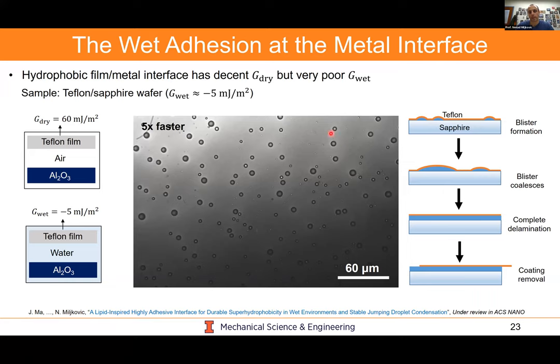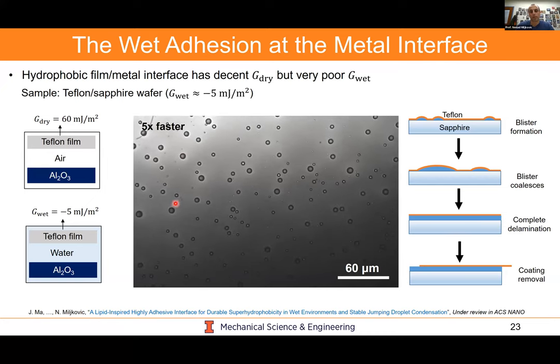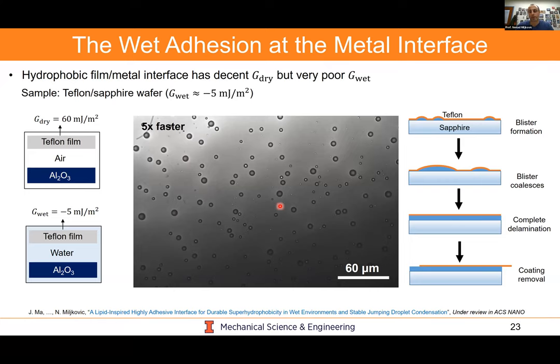You definitely don't want that. Oh, now it's playing. What you're seeing here is condensation. You can see blisters forming, and just like that, the coating is removed. This coating right now is floating. Let me see if it plays again. It may not. Oh, here we go. So: condensation, droplets, blisters, coalescence, done. The coating itself is floating and moving around. Again, this is all because of thermodynamics. You want good wet adhesion, not necessarily good dry adhesion.